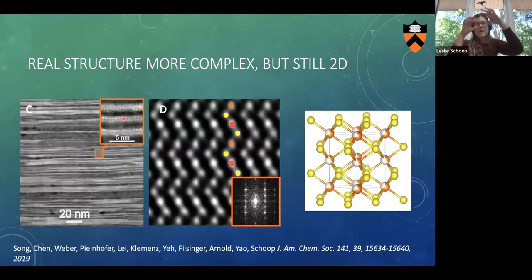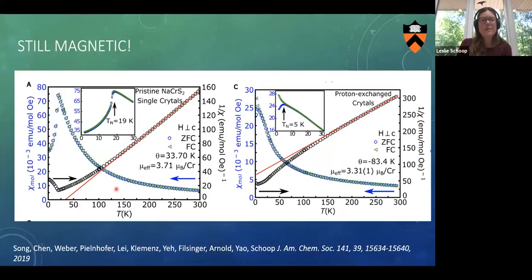So we were interested in the magnetic properties of this new layered material, and if there's still magnetism in the system. And good news, there is. This is the original compound. The sodium chromium disulfide is an antiferromagnet, and the proton exchange material still has a magnetic ordering peak, but also a pretty large negative Weiss temperature, which indicates some magnetic frustration in the system.